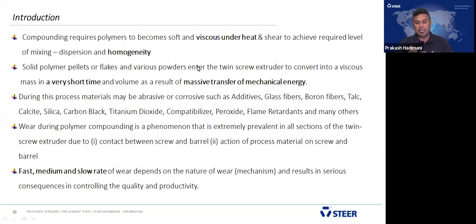Compounding requires the polymer to become soft and viscous under heat and shear, to achieve the required mixing and dispersion and form a homogeneous mixture. Polymers are solid, in the form of pellets and flakes, and various powders enter the twin screw to form a compound. The mass has to form in a very short time, and this results in a massive transfer of mechanical energy.